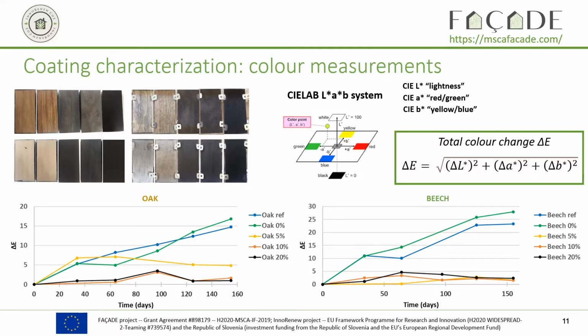And here you have the results for oak and beech. You can see that there is the same trend for both types of wood. The reference is in blue, and for the reference, the total color change is only increasing. So the more time passes, the more the color is changing. When you add the oil without biocarbon, you have the same tendency. The color change is always increasing. And this is not really surprising, because the oil at the surface is also affected by the UV, and it turns more and more yellow. And you also start to have the growth of microorganisms at the surface.